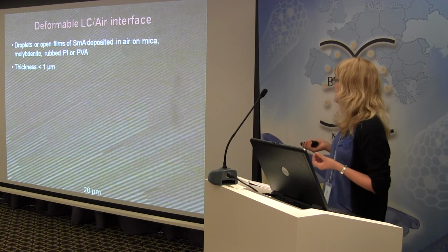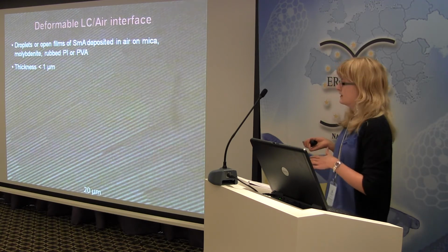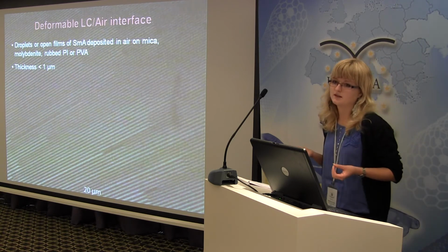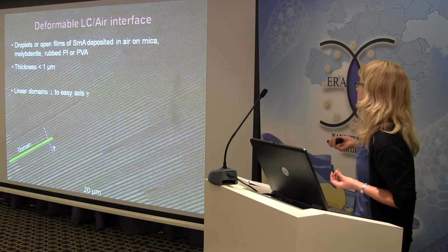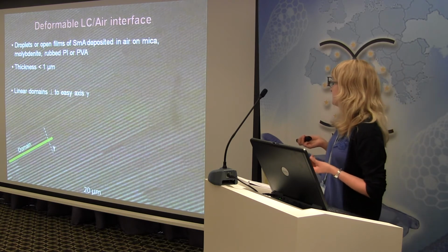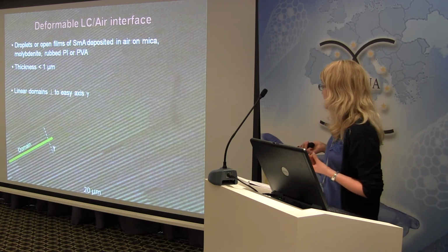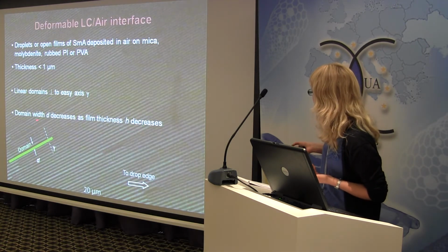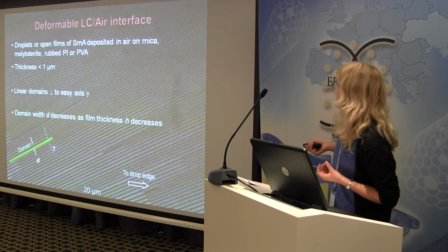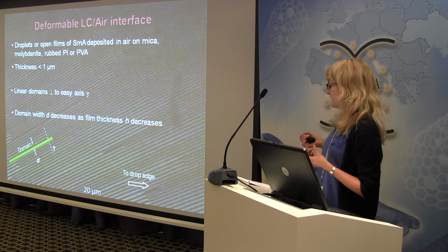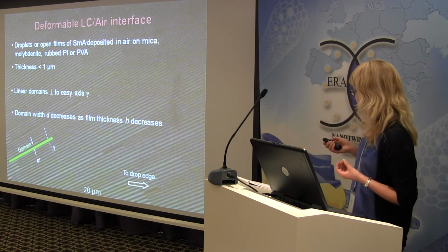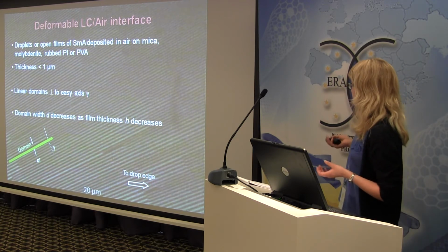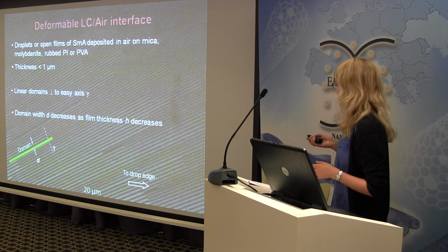The important thing here is that the thickness of the liquid crystal film should be about 1 micron and less to create the linear defect arrays. And linear domains grow perpendicular to the easy axis, and the period of domains decreases when the thickness of the drop decreases.